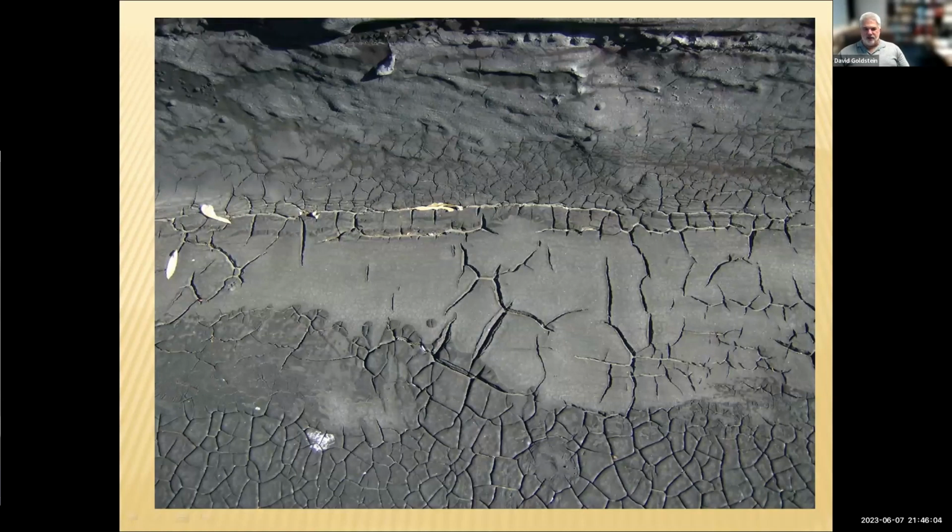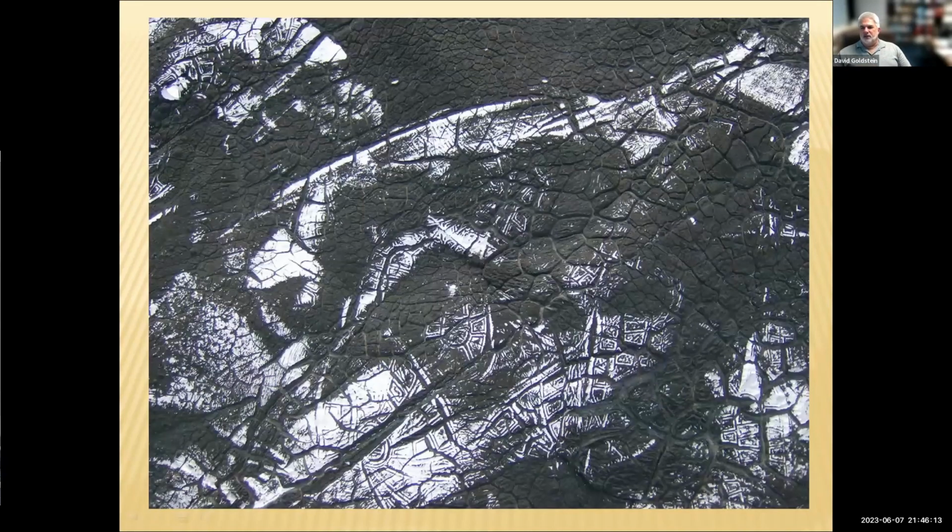You get the scaling or the alligatoring, and it's pulling apart. It's like fissures and crevices that are in there. Same thing here, but on top of that, you see the boot prints. Somebody walked on this when it was hot.